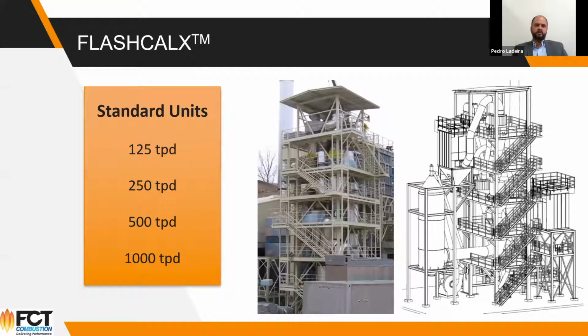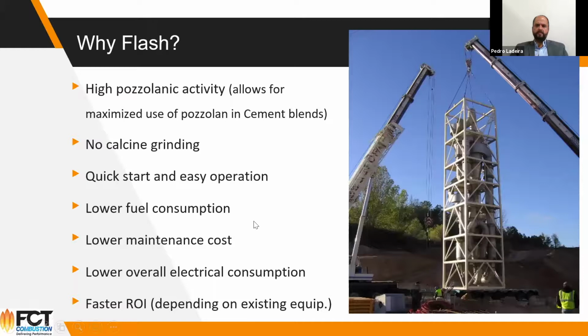Of the standard units that we have, we talk in tons per day. We're talking about over 1,000 tons per day of flash calcination. It's already achievable. And there's an actual installation that you can easily put together, depending on the size. You can also truck it, using mobile equipment and reducing the erection cost. But what we finally have with the flash calciner is a very reactive pozzolan. You probably don't need to grind the calcine, as the material is not prone to melt or to re-agglomerate. As we've seen, there's a quick start and easy operation of the plant.